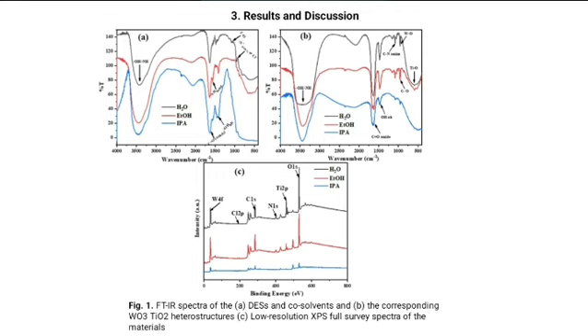Besides the vibrations that are attributed to tungsten to oxygen and titanium to oxygen bonds, they were assigned to the sharp peak at 960 wave number and the broad peak at 591 wave number, respectively. Now for the low resolution XPS full survey, it showed that the interacting atoms were well represented, revealing the different groups of the tungsten 4F, chlorine 2P, carbon 1S, nitrogen 1S, titanium 2P, and oxygen 1S regions.